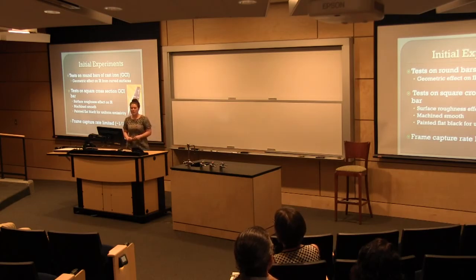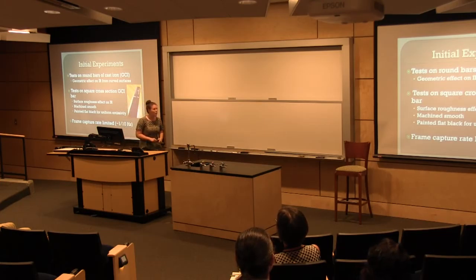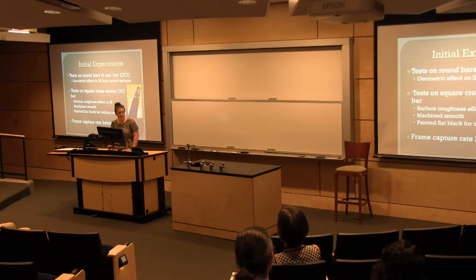So initial experiments, this is when we started experimenting at Loyola. We actually started with round test subjects of gray cast iron, which didn't really work out. There's a lot of things that we had to go through and change and tweak here and there. And this was the first one of our hiccups. But we were finding that there were problems with the curved surfaces viewing through the IR camera, so we couldn't get an accurate measurement of the temperature at certain points.